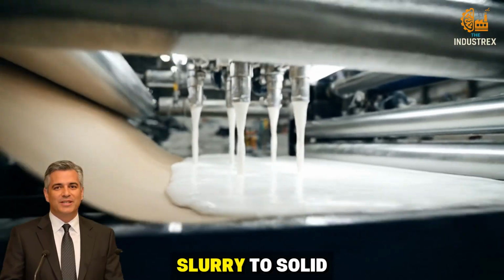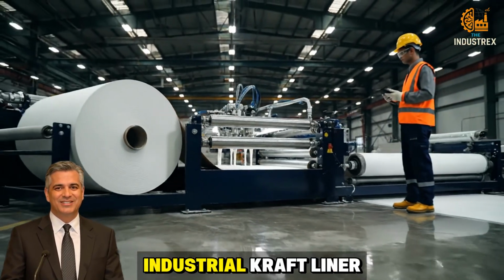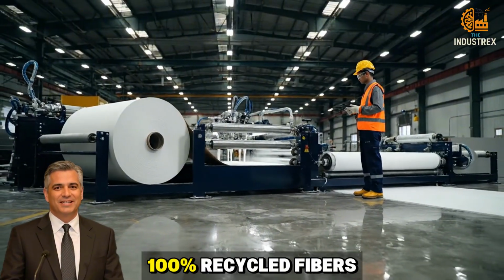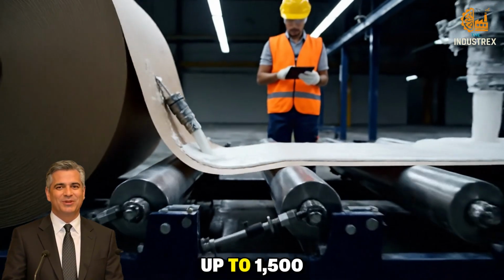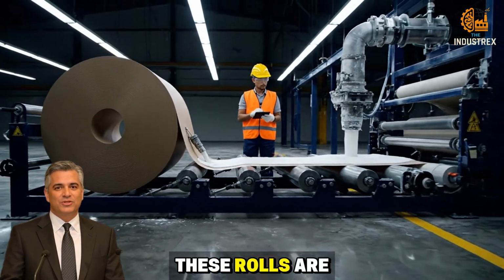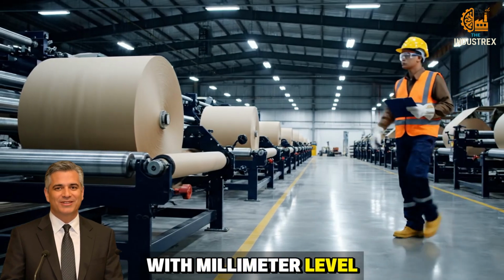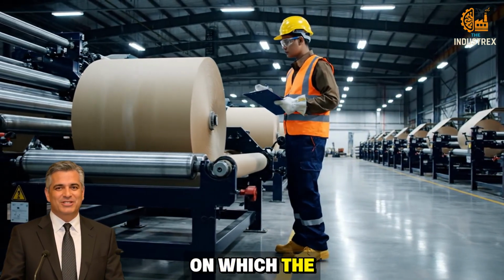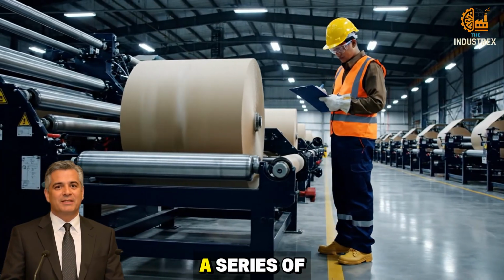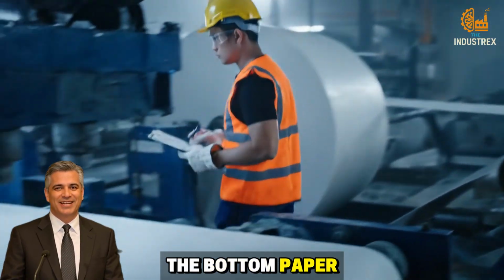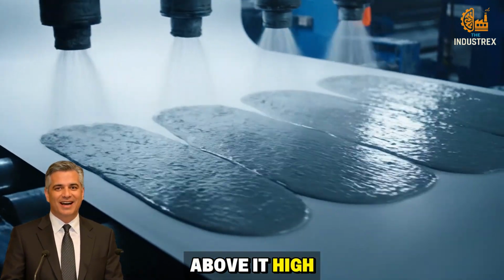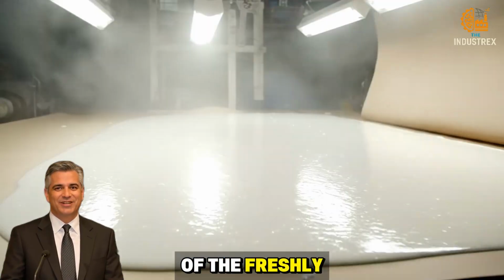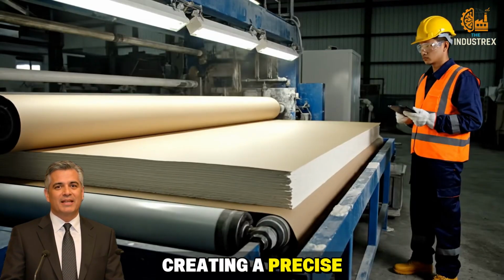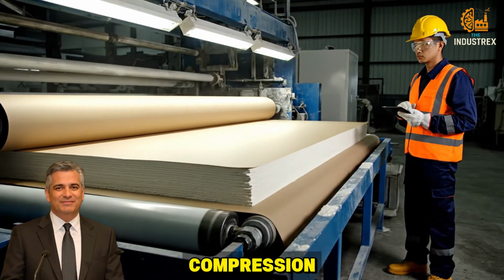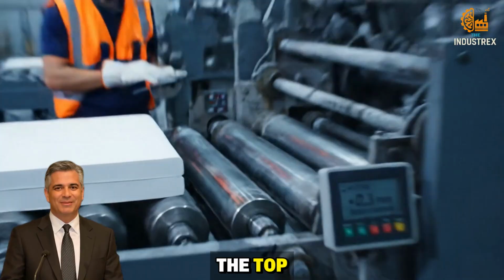The transformation from slurry to solid panel begins with paper, industrial kraft liner, often made from 100% recycled fibers, arriving in rolls up to 1,500 meters long. These rolls are fed into the production line with millimeter-level alignment, forming the foundation on which the gypsum core will bond. Unrolled and tensioned by a series of servo-driven rollers, the bottom paper layer glides forward smoothly. Above it, high-pressure nozzles spray a continuous layer of the freshly mixed gypsum slurry, creating a precise, even spread. Then comes the compression. A roller table presses gently across the top, smoothing the slurry while applying the top paper layer.